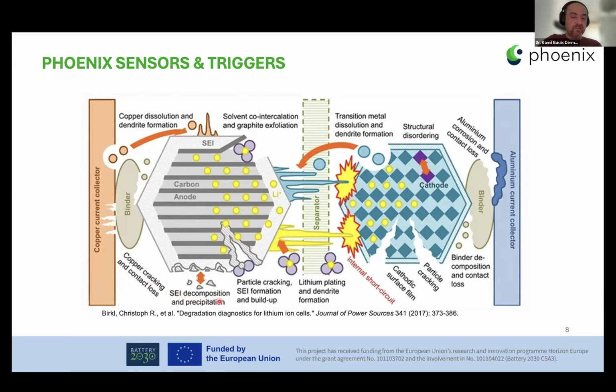The SEI is an inevitable and indispensable component that ensures the long-term stability of the batteries. The SEI can decompose or reprecipitate during the operation of the cells, which is also one type of degradation mechanism. The particle can crack and SEI formation can continue and keep building up, leading to unwanted levels of SEI formed. That will also jeopardize the performance after all.